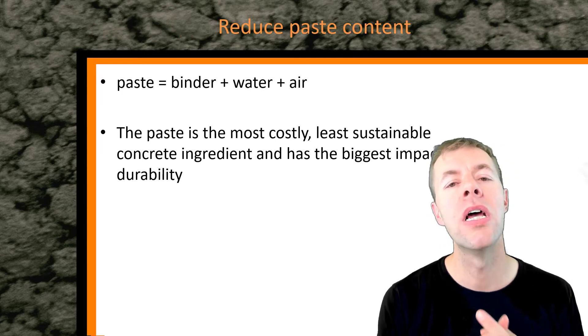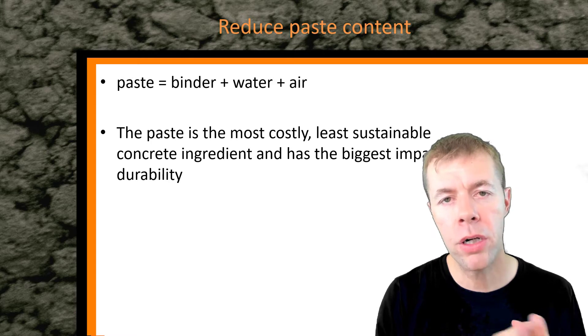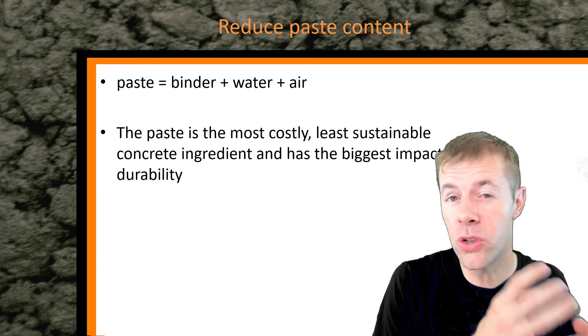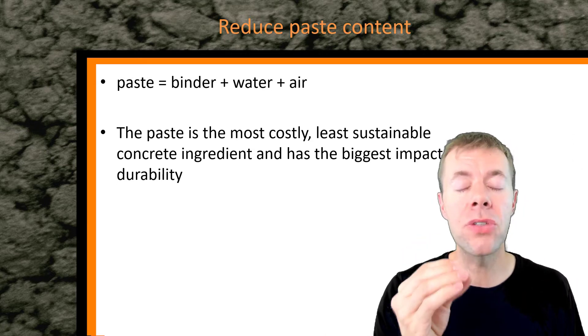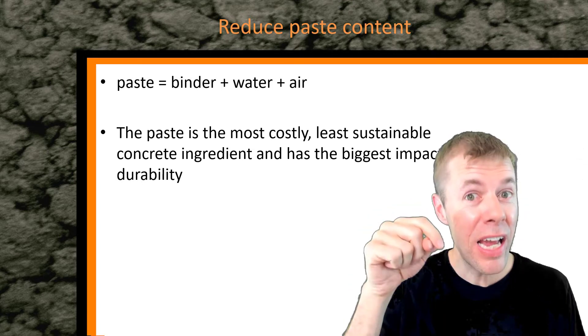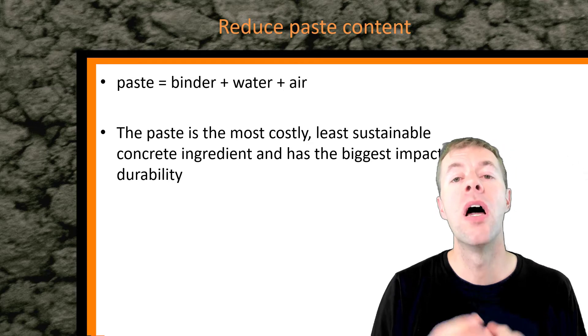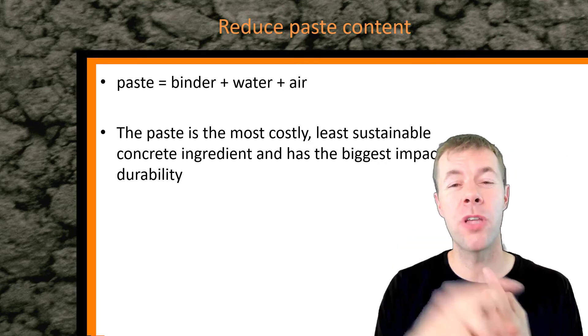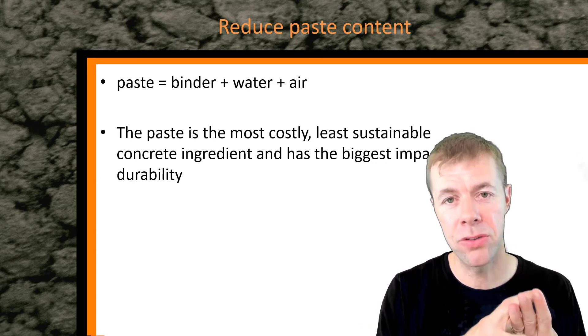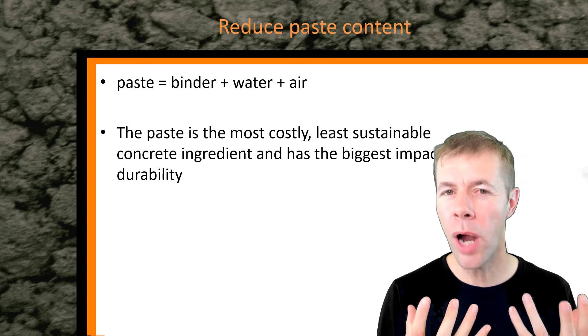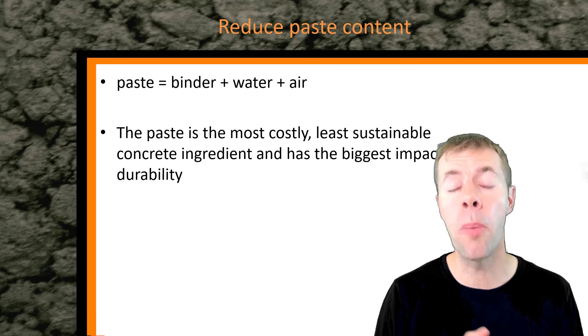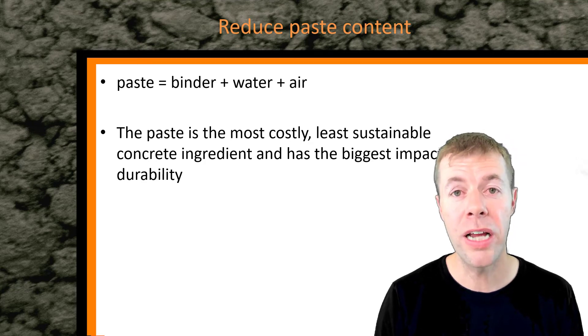What's paste content? Paste is your binder plus your water plus your air. You don't want to have too much and you don't want to have too little. I have a mix design procedure that gives you a good first guess — I'm going to link to it in the description below. We don't want excess paste because it's the most costly, the least sustainable concrete ingredient, and has the biggest impact on our concrete's durability. A lot of times you just have to trial batch your concrete and see.